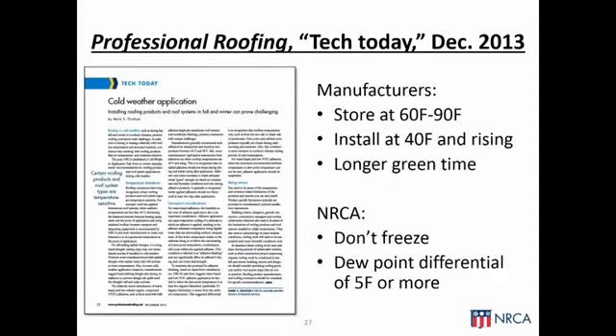In December of 2013, my column dealt a little bit with cold weather applications and some of the struggles that are out there with water-based bonding adhesives. For example, manufacturers are saying storage temperatures should be between 60 and 90 degrees Fahrenheit. Installations should only be conducted when temperatures are 40 degrees and rising, and realize green times with water-based adhesives are longer, in some cases significantly longer, than they were with solvent-based adhesives.